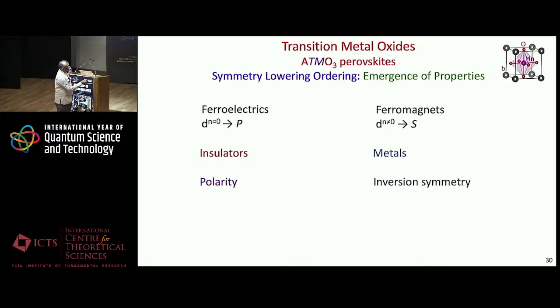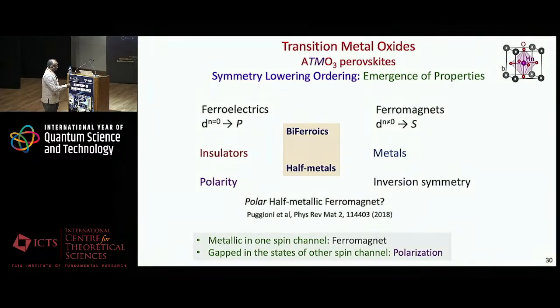Whereas if you want to have magnetism, you need dn not equal to 0, which gives a spin. And they're typically metals. These are insulators, and these are polar, and metals are typically centrosymmetric. They're non-polar. And in fact, now we will be introducing a class of metals we call unusual metals, not strange metals. In the sense, these are non-centrosymmetric metals. But even more interestingly, we want to combine them. We make half metals, meaning it's metallic in one spin channel, and it's gapped in the other spin channel. So one spin channel favors ferromagnetic itinerant electrons, and the other spin channel has bound electrons which support ferroelectric polarization. And they are also coupled with each other in a beautiful way.